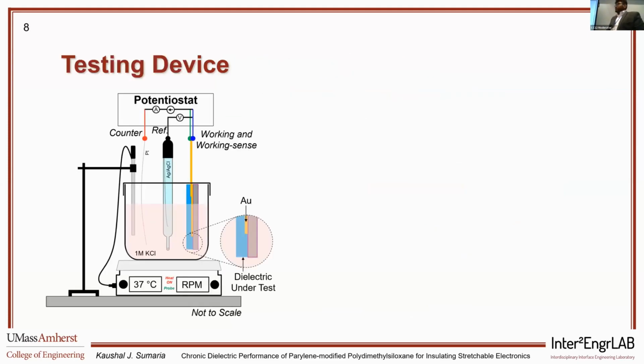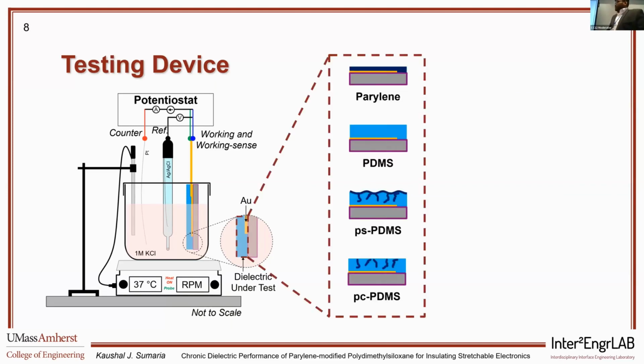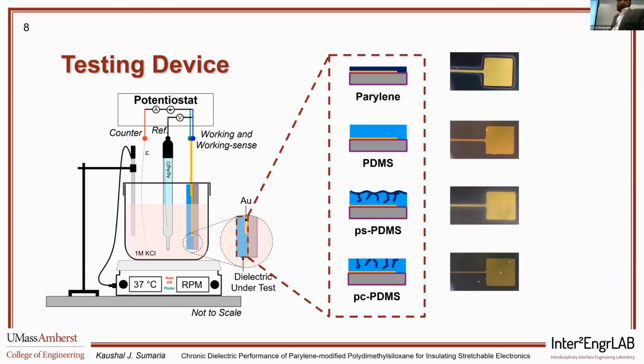For the testing, we use a 3-electrode setup with a potentiostat. So the potentiostat outputs current between the counter electrode and the dielectric material, and the reference electrode measures the voltage. That's how we can calculate the impedance. The bath we are using here is a 1 molar KCl to provide a high ion-rich solution around the dielectric being tested. So the 4 samples are tested, which look like this one after the fabrication.